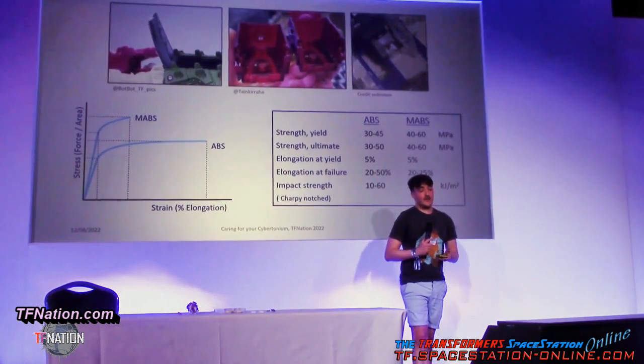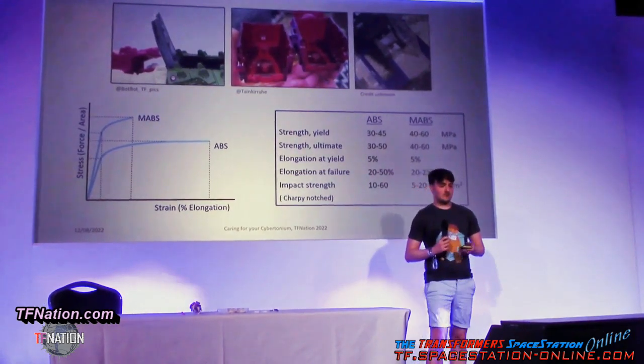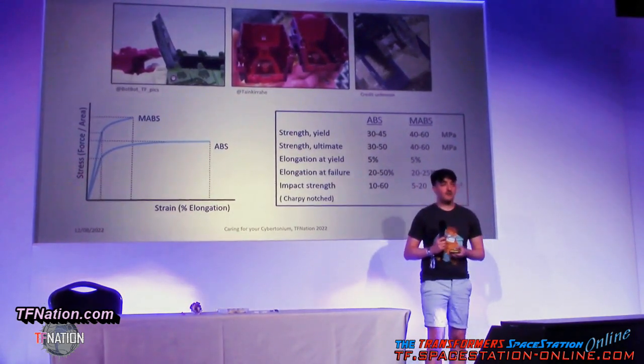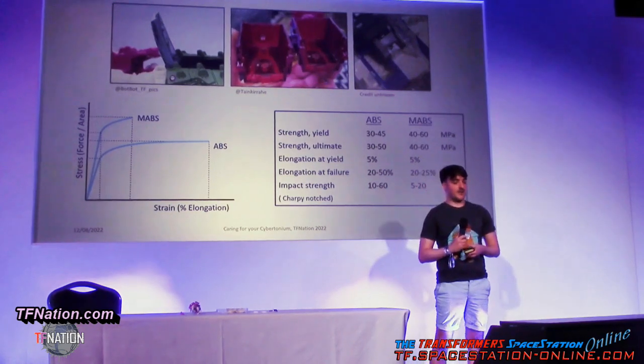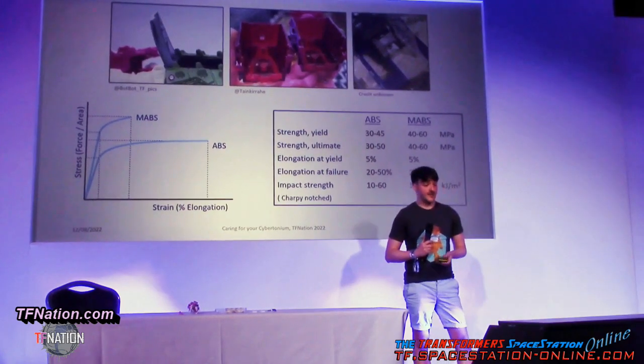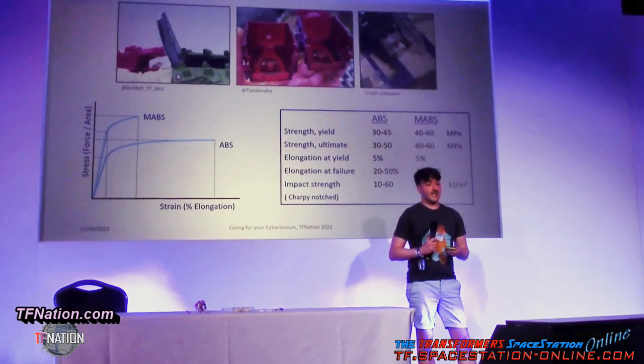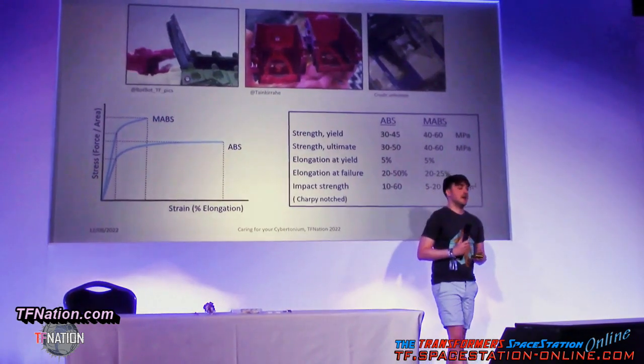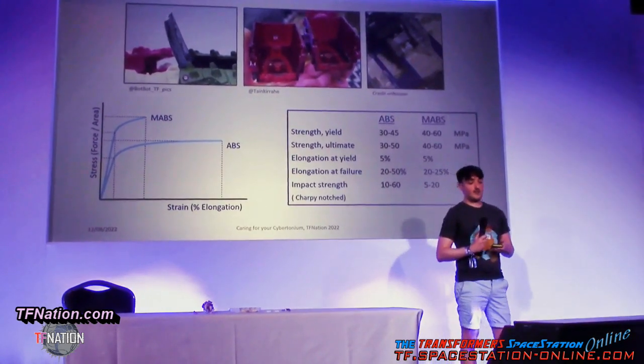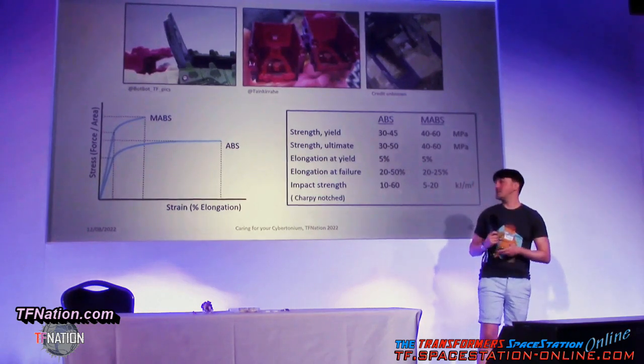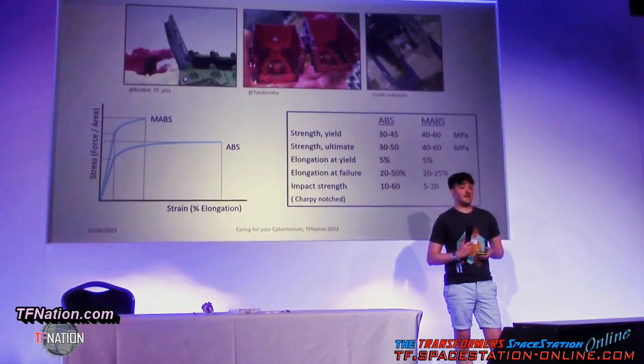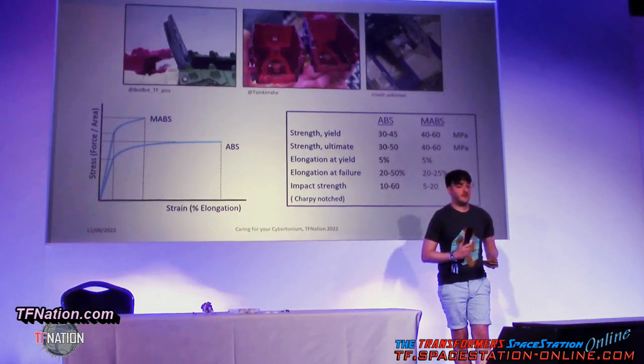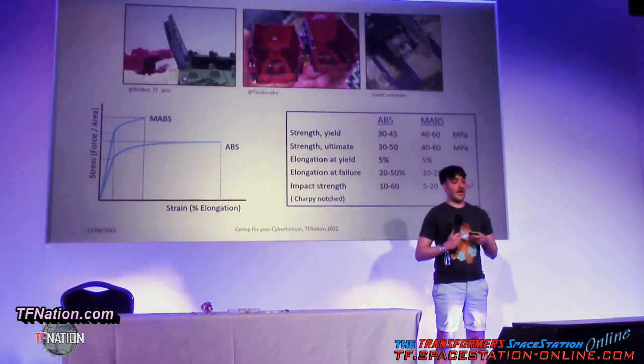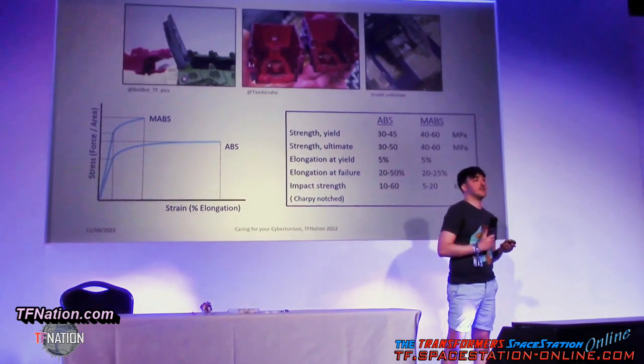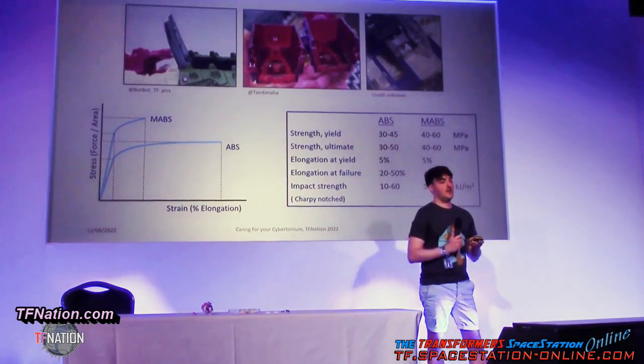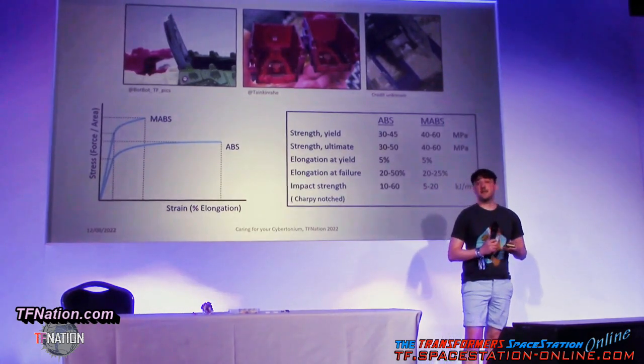In fact, MABS can take, I think, about 15 or so higher megapascals at yield and at failure. And ABS, so the opaque version, can actually stretch up to 50%, so almost double at failure compared to MABS. So this is quite illustrative. If you apply the same amount of force, your opaque plastic is going to stretch, and your clear plastic is going to break.